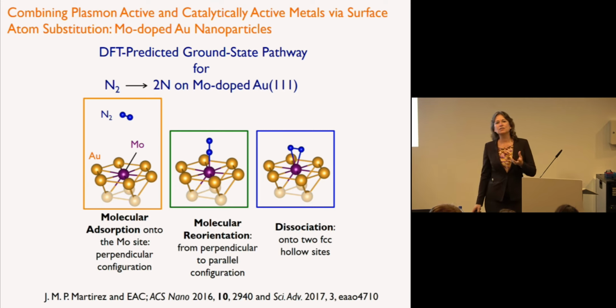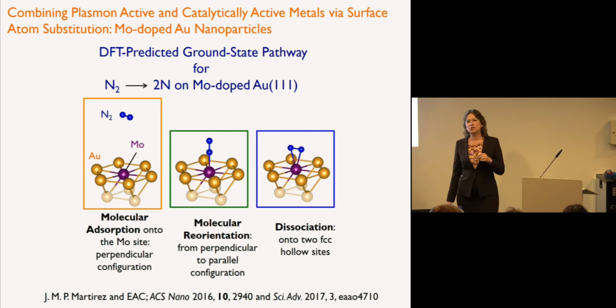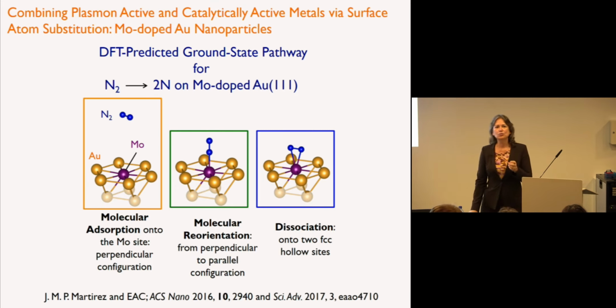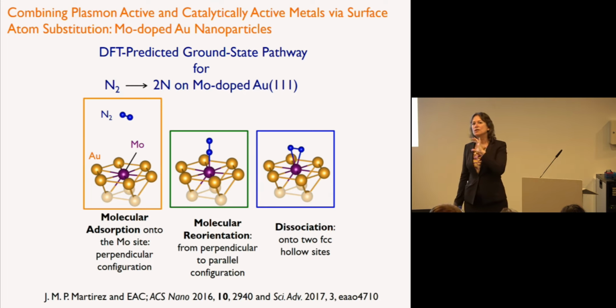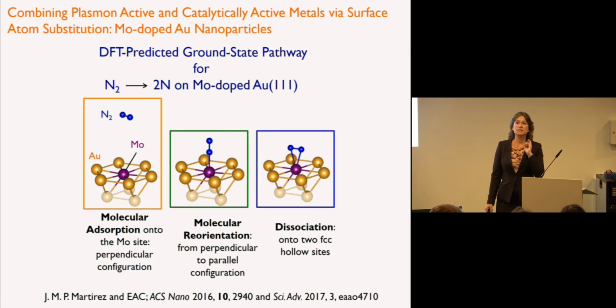In the case of hydrogen, I said we have evidence for charge transfer. And that makes sense because, in fact, H2 minus is a stable molecule. N2 minus is not stable, and so you don't get charge transfer to nitrogen. You have to go through a different process. And we see, from the analysis of the wave functions, that we don't get charge transfer. What happens is actually a resonance energy transfer process has to be active.